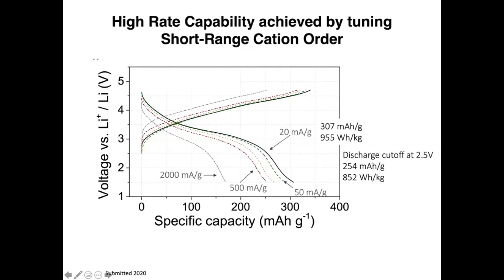For example, 50 milliamps per gram, even at 500 milliamps per gram, so almost 2C, we get very good rate capability, very good capacity. And we've even discharged this material at 2 amperes per gram. So relatively speaking, an 8 to 10 C rate. And this is purely done by optimizing the very local short range order.